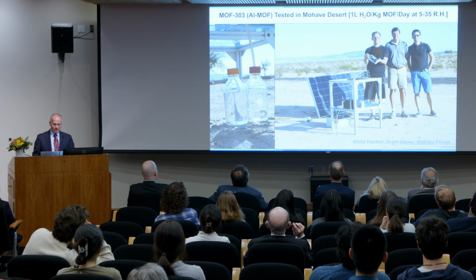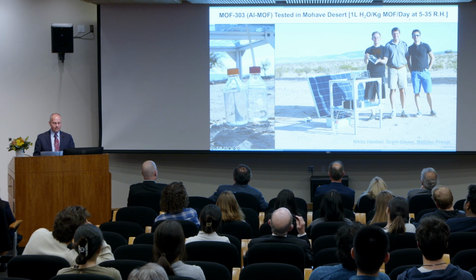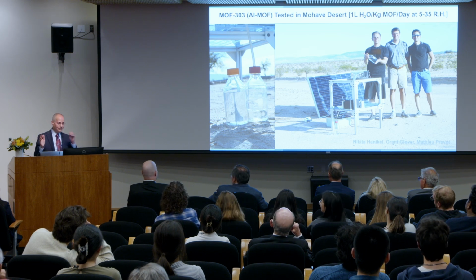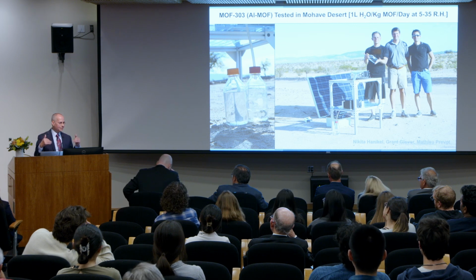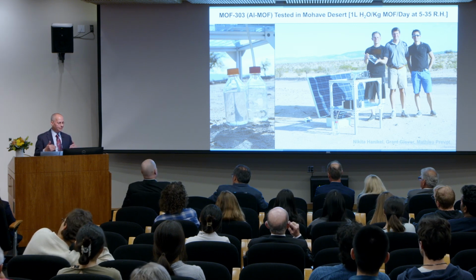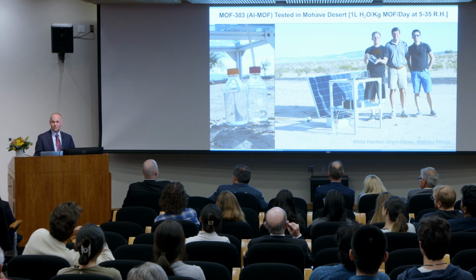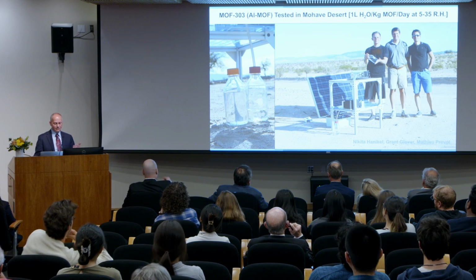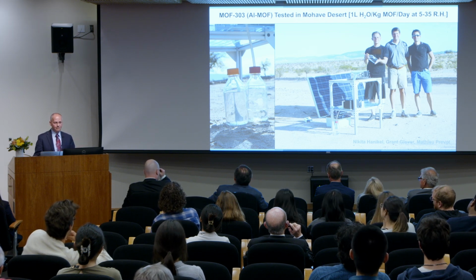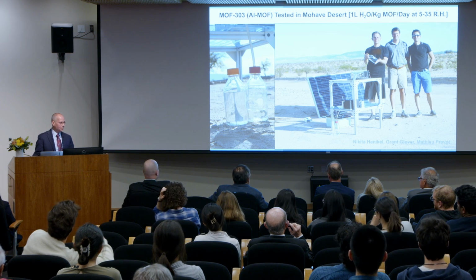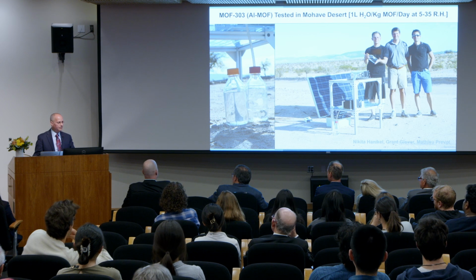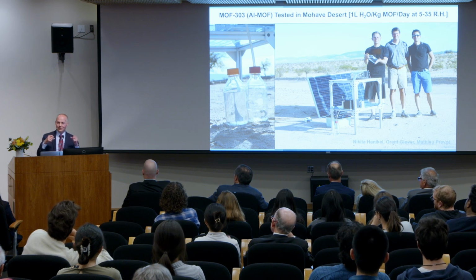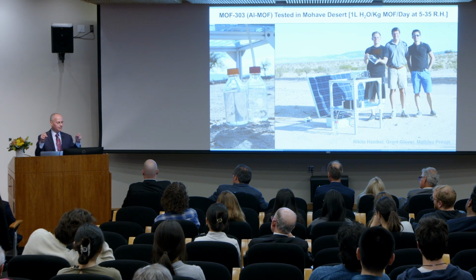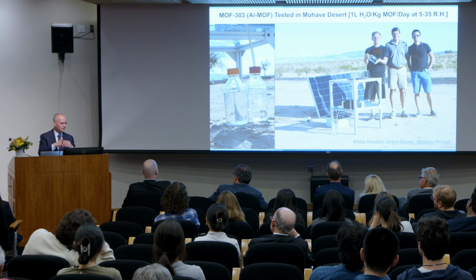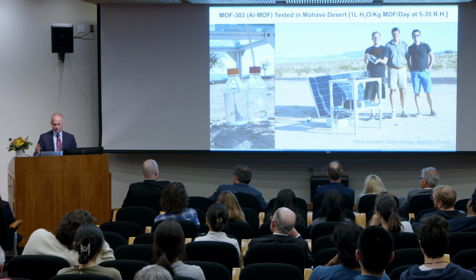From that experiment, they harvested 1 liter of water per kilogram of MOF per day under arduous arid conditions. That kilogram of MOF is sitting there in the device, giving you 1 liter a day for years, because the MOF is extremely stable and it can cycle. This MOF has been cycling for the last 3 years with no degradation. So we think that this MOF is good for at least 5 years or more. And at the end of the MOF journey, you can separate the metal from the organic using acid and reassemble the MOF in water in a zero discharge process, invented by BASF.